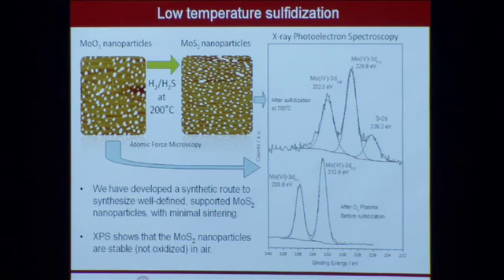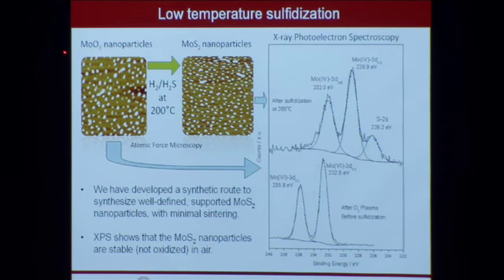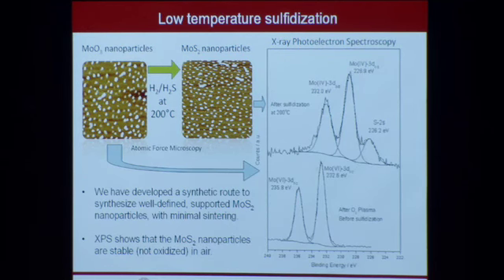So let me show you some images. These are some AFM images of the MoO3 moly oxide nanoparticles immediately after the oxygen plasma step. We reduce these in the hydrogen H2S to sulfidize them, and you can see that the particle size has changed a little bit, likely due to a change in the lattice constant of MoO3 versus MoS2. It shrinks a little bit, but you can see that they haven't sintered, and that's a very important point. When you heat things up, oftentimes these nanoparticles are mobile and will agglomerate, but you can see that that has not happened. We use X-ray photoelectron spectroscopy to keep track of the oxidation state of our materials before and after the furnace treatment. Beforehand, we see a very clean signal for Mo6+, MoO3 in other words, which is exactly what we'd expect.